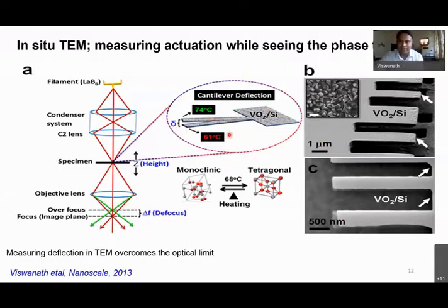I used the focused ion beam to make cantilevers like this. Of course, at the edges, the cantilever is still electron transparent. The thickness, I would say, is still slightly thicker, around 200 nanometers. So what we have done is, instead of having a static sample,